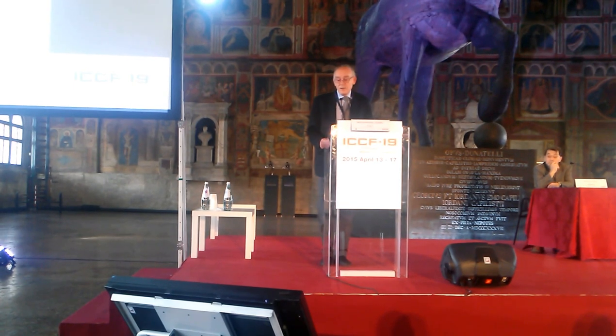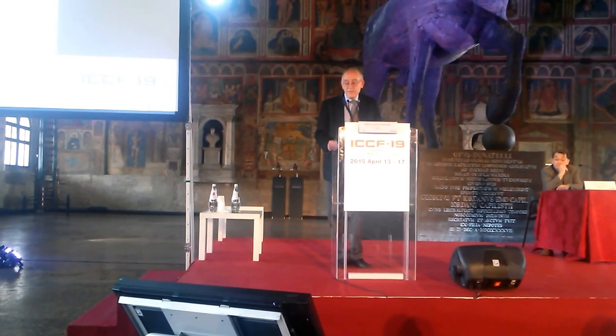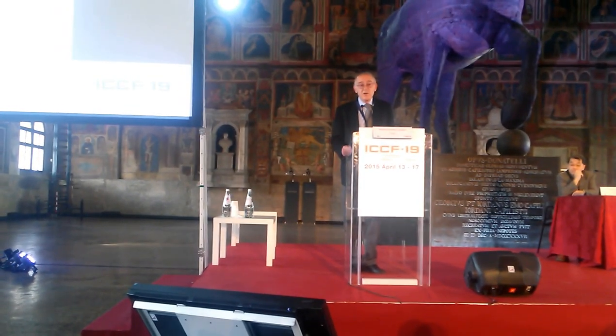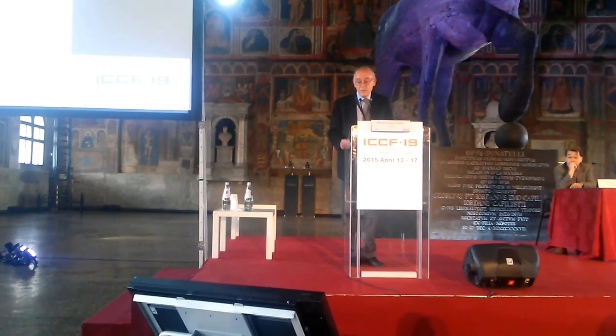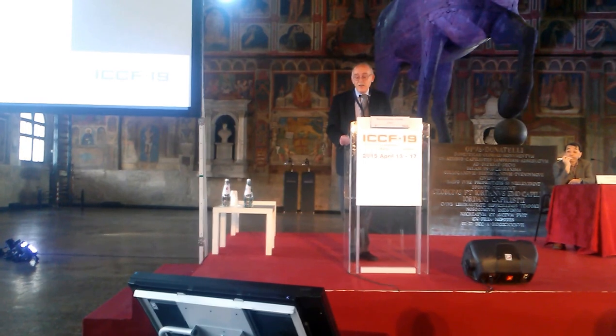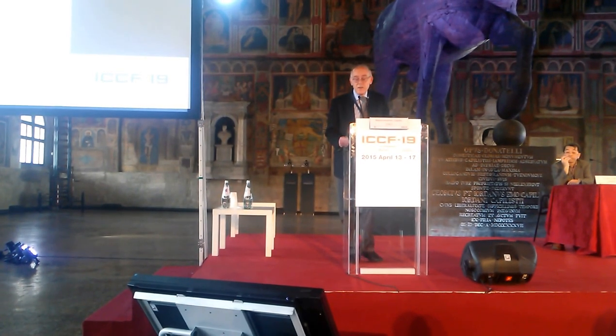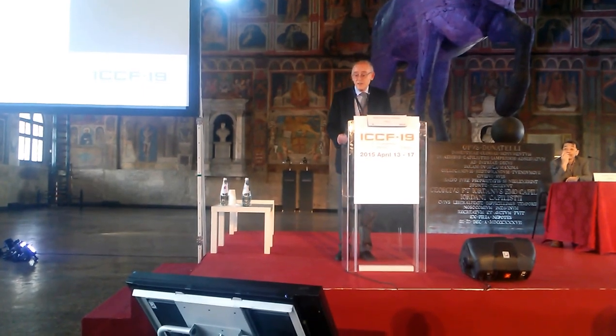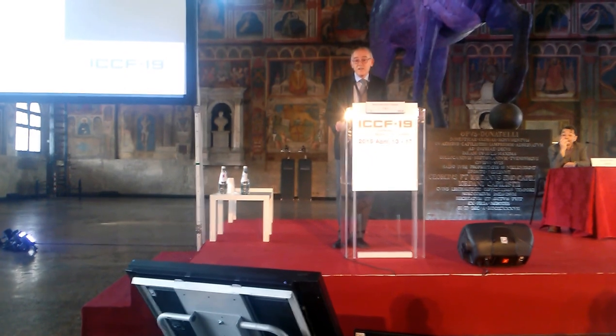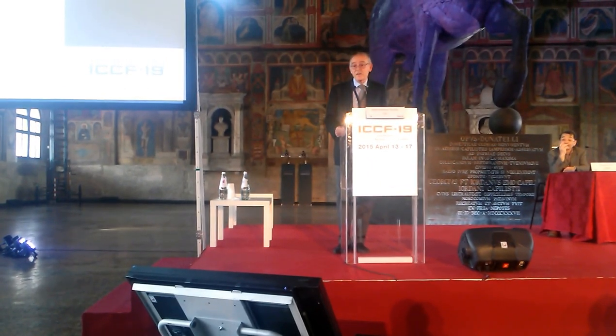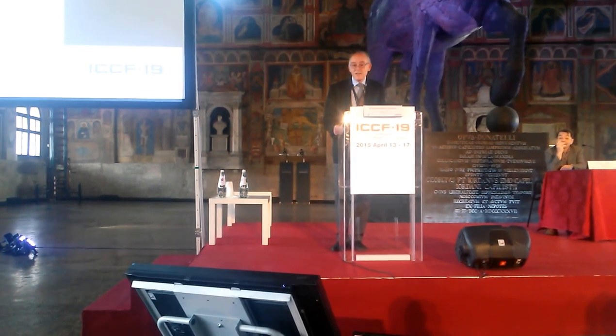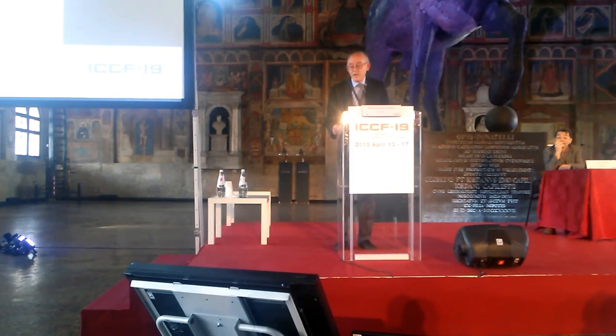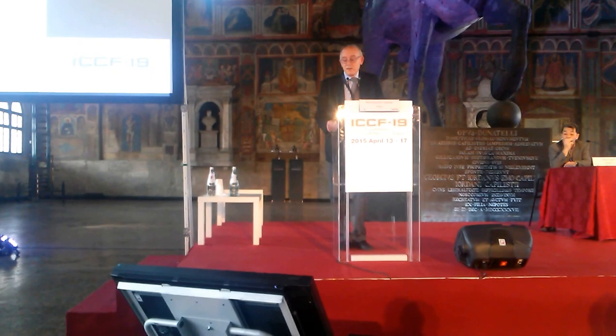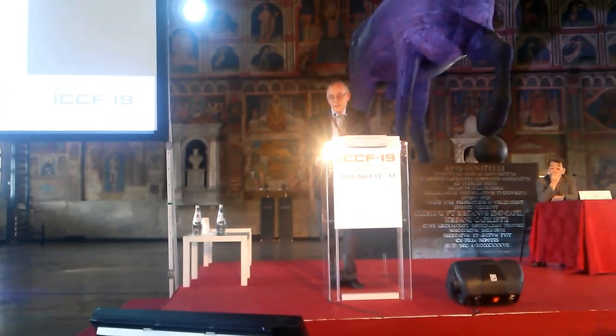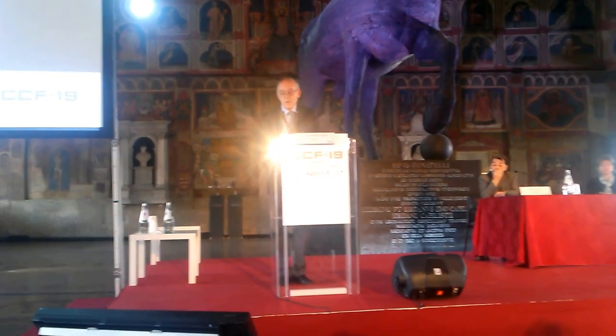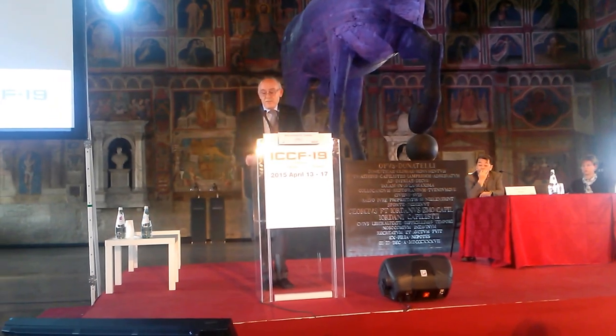And you can see on the right of the slide, experiments done with deuterium in Lecce. At that time, we were able to make these experiments with deuterium. And even without laser stimulation on the deuterium samples, we could recognize hot spots, many hot spots. The density of hot spots in this case was about 2,000 per square centimeter. The experiment lasted 10 weeks, by the way, so quite a long time. And with deuterium, we had more anomalies than with the hydrogen. With hydrogen, we needed to have the presence of the laser.